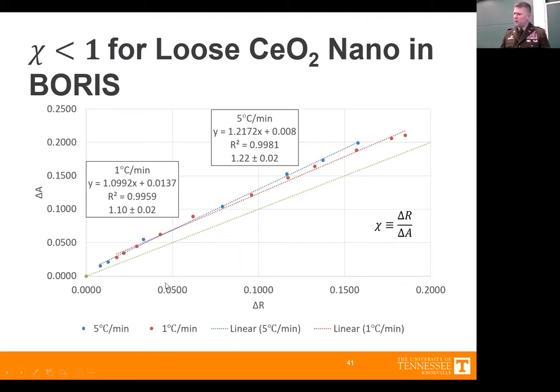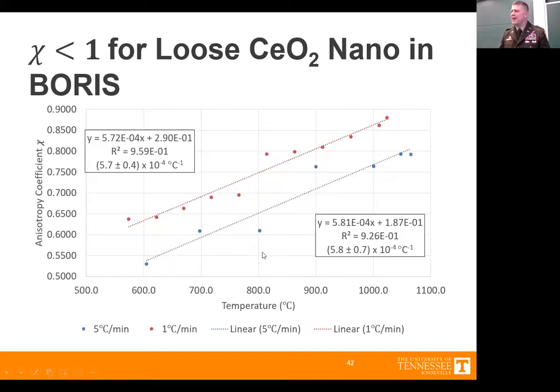This graph here is showing 2 different heat rates of the nano size powder in the XRS-4 system. On the y-axis, I have the axial shrinkage. On the x-axis, I have the radial shrinkage. Again, this green dashed line is the isotropic case, but you can see both data sets are shifted significantly above that isotropic case.